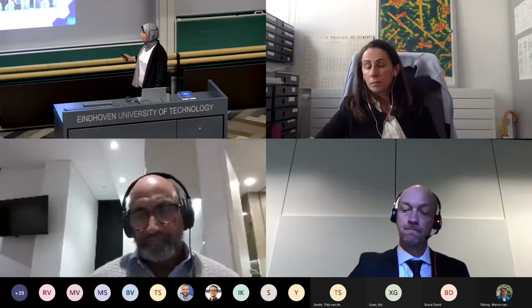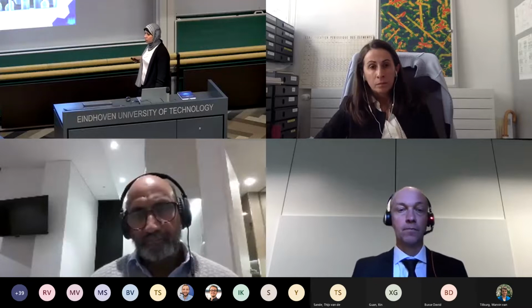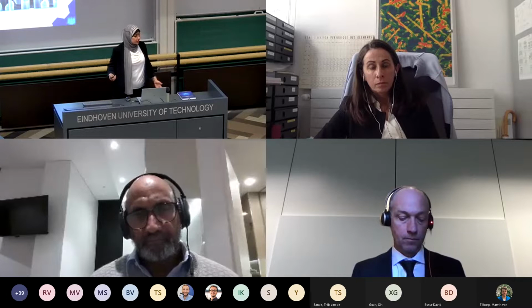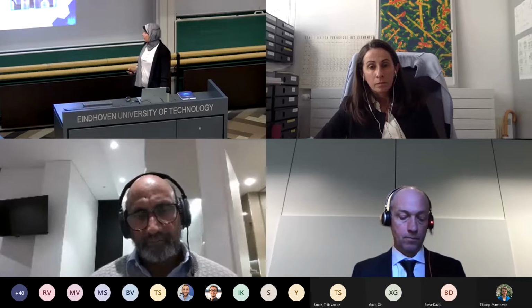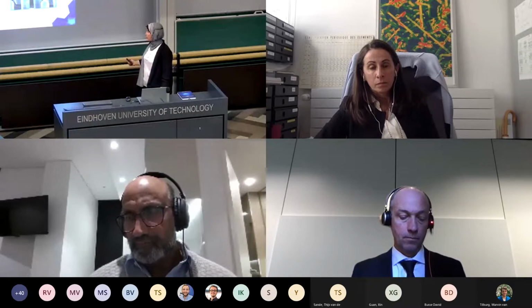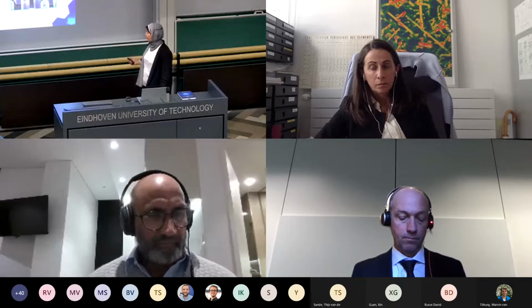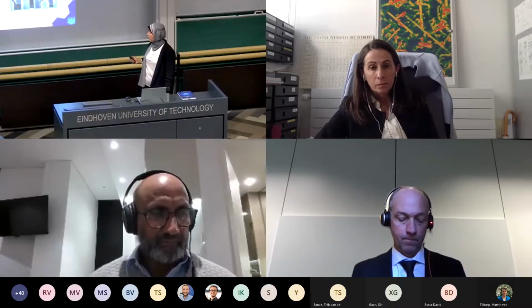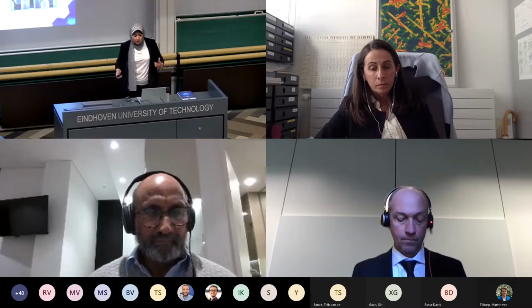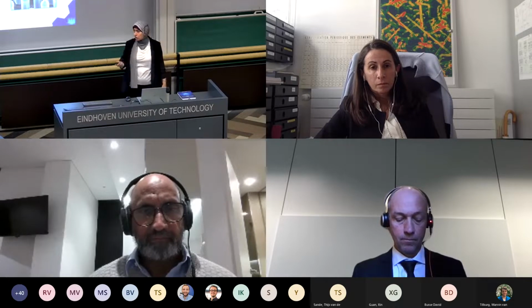And the nice hexagonal shape with the flat side walls is an indication of high quality crystal material. Then we study the optical properties of these nanopillars by shining light on them, and then we study the emitted light from it by a camera. And the output of this camera is light spectra, as you can see here. And we nicely managed to tune the composition, or let's say the mixture of silicon and germanium in these structures.